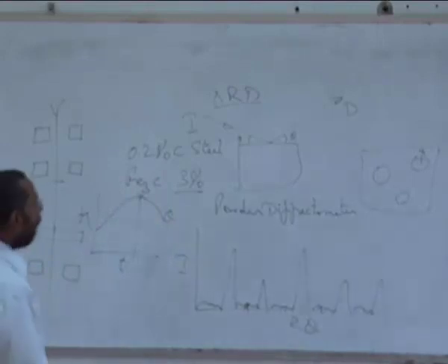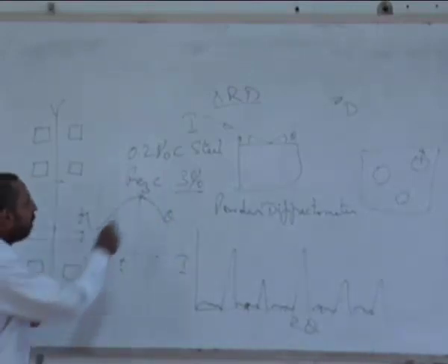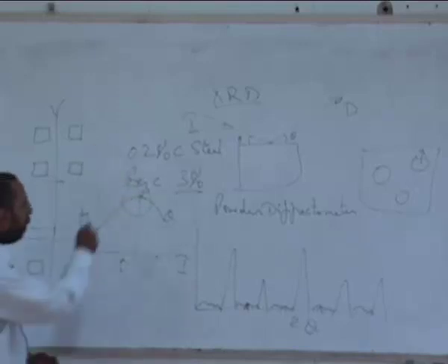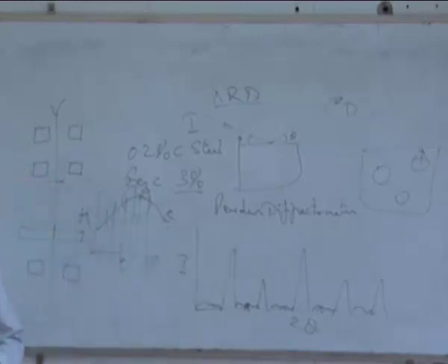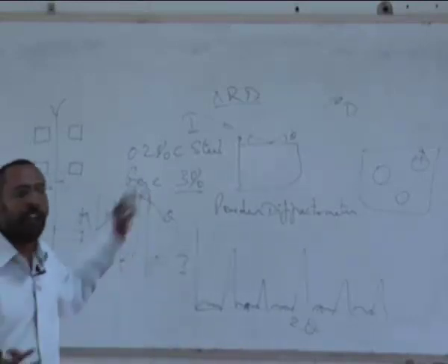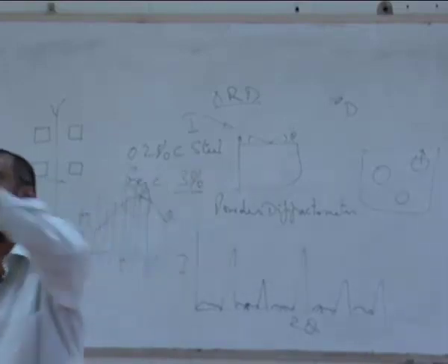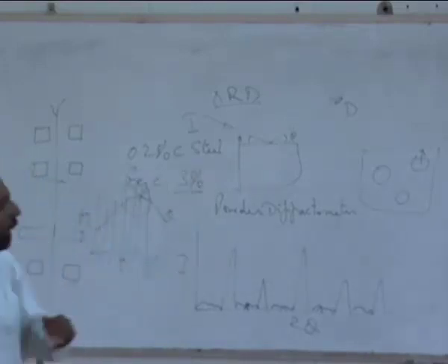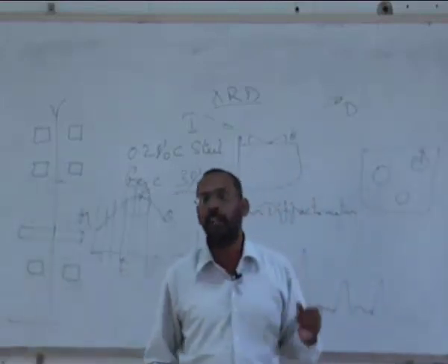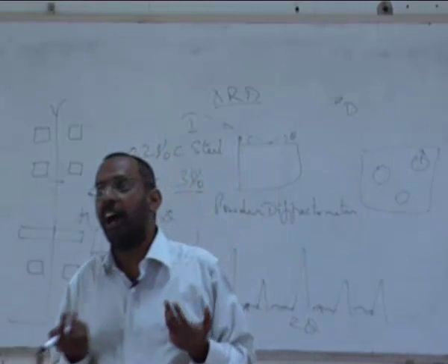How is it that now I am able to confidently say that it is semi-coherent precipitates which will give you this high strength? It is because I have been able to do microscopy of these samples which are aged for different timings, and they were all put into a TEM, and people were able to find out what are the crystal structures of these precipitates, not only finding out the sizes of these precipitates, but also being able to find out this kind of orientation relationships, and from that find out whether they are coherent or semi-coherent.